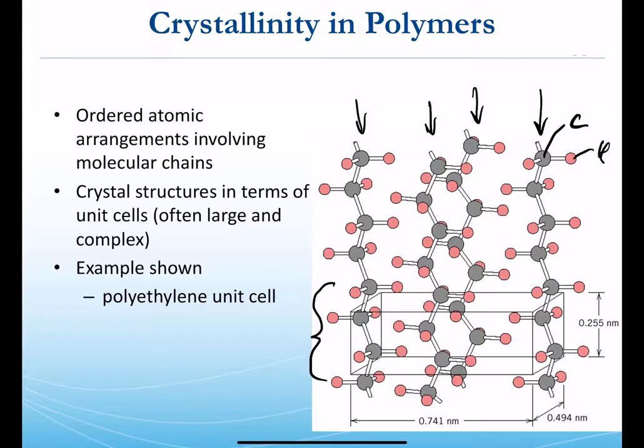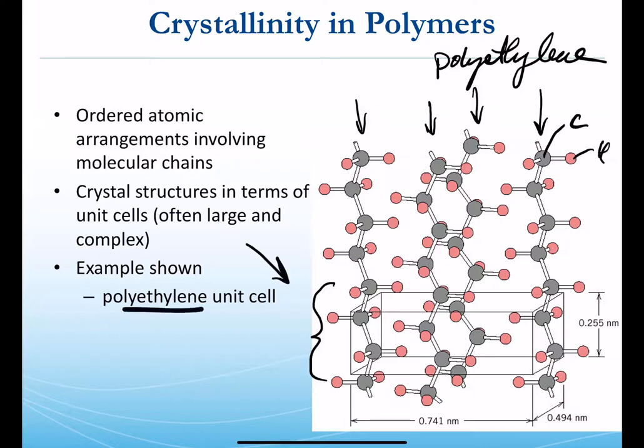The unit cell describes the minimum repeating feature that can describe the pattern in all three dimensions — that's the unit cell of a crystal of polyethylene. So here we have an ordered atomic arrangement involving molecular chains. The crystal structure in terms of unit cell is indicated, and we've seen that it's the polyethylene unit cell. Even though polymers are often cartooned as noodles, they can pack and crystallize in very regular formats, like we've seen with metals and even ceramics.